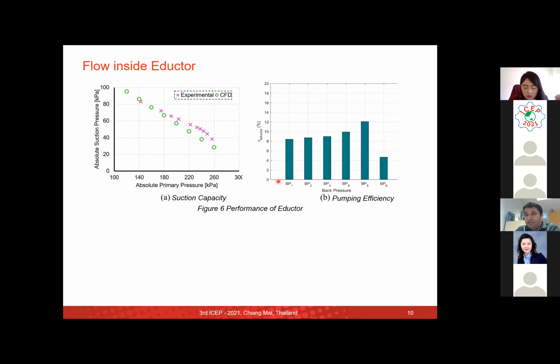And when we talk about the capacity of vapor transfer within the eductor, we could see efficiency of up to 12% at different back pressure conditions. When we did the experiments, we could measure the efficiency up to 12% for these eductors when they are actually pumping. So this is the maximum vacuum generation capacity, and this is the maximum pumping capacity, or let's say maximum efficiency for pumping.